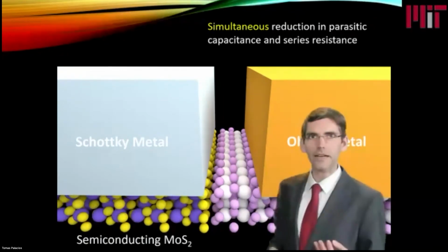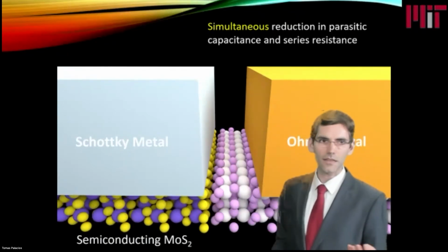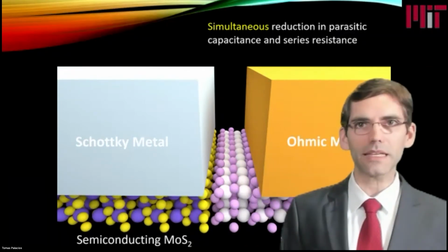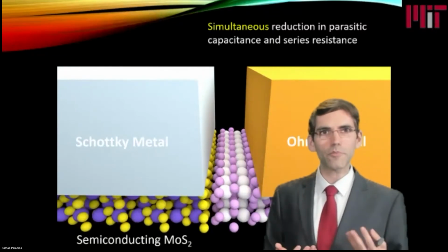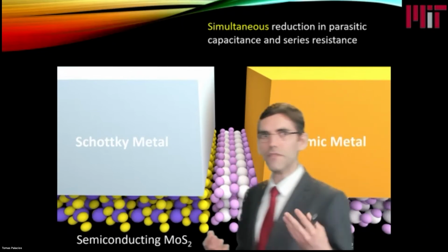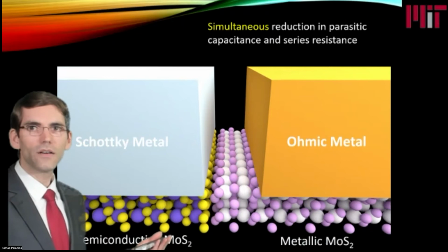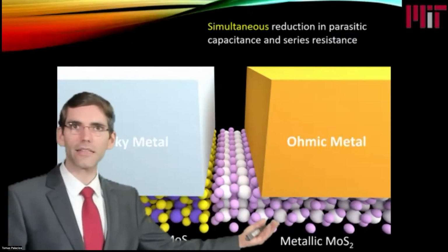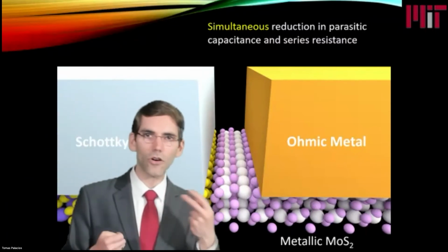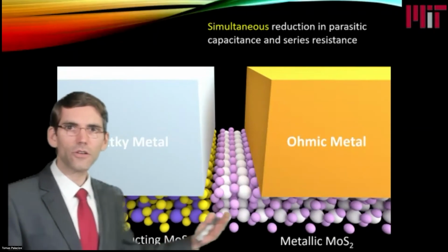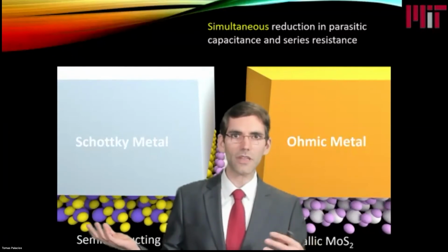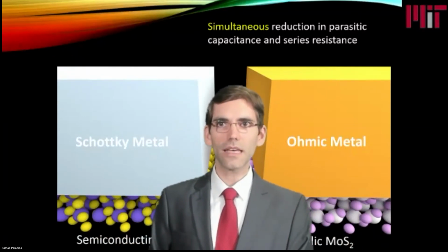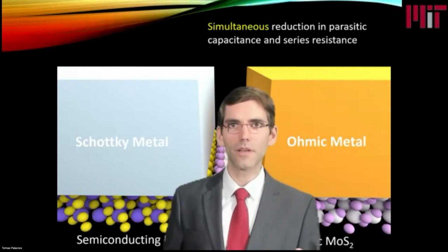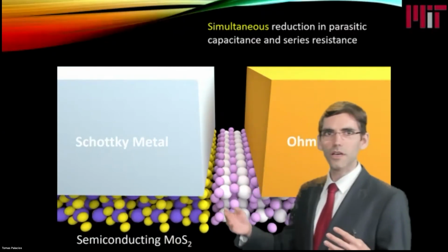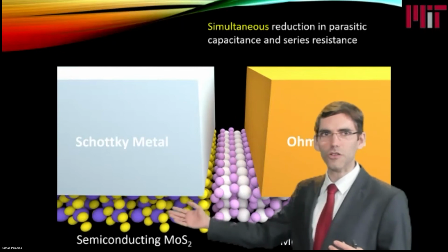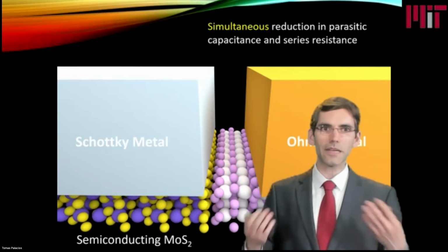And the way we built that rectifier was by using molybdenum disulfide and using some of the truly unique material science related to this material. For example, one of the properties that I find most interesting is the fact that you can have two different kinds of molybdenum disulfide, either semiconducting or metallic. Same material, just a change in the phase, in the way the atoms are organized, makes the material be a semiconductor or a metal. And you can go from semiconducting to metallic behavior by just exposing the molybdenum disulfide to specific chemicals. And this is very interesting because it allows us to develop truly self-aligned heterojunctions between semiconductors and metals without the need of expensive fabrication processes.